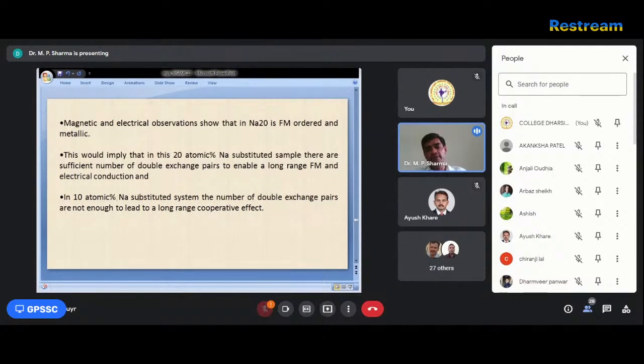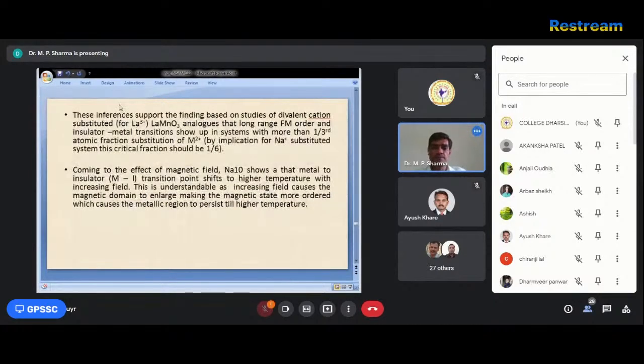So in sodium 10, the number of double exchange pairs is not enough to realize the long range property effects. So these inferences support the finding based on the study of the divalent cations. Means in LaMnO3 it is shown that if you substitute with divalent cations, implied here as sodium monovalent cation, that gives the fraction of 1/6.